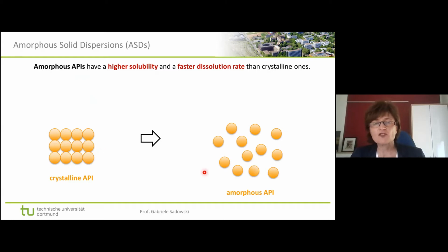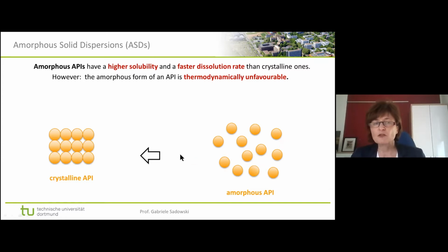The disadvantage is that the crystalline state is much more thermodynamically stable. So once you have somehow managed to produce an amorphous API, it will recrystallize. This is what it wants to do: it wants to lower its energy, and it will recrystallize. And that means you are then again back to the crystalline API.